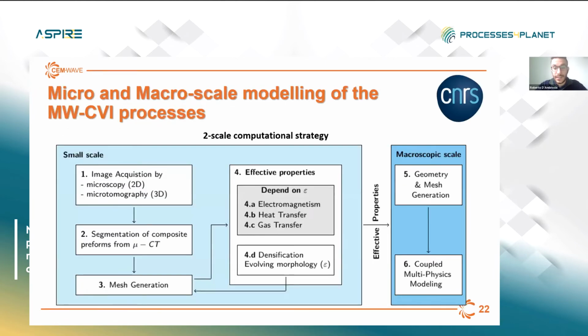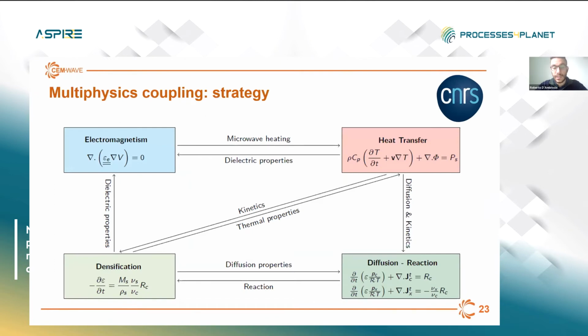Another crucial activity regarded the multi-physics, multi-scale model of the microwave CVI processes, which have been carried out at CNRS in Bordeaux. Here, it is depicted the modeling strategy, which covered 3 different scales, from the intra-fiber bundle scale of tens of micron up to the whole part scale. You can see that in order to model the microwave CVI process, we need to solve the conservation equations for 4 different physical problems. And also, we need to know the laws providing the change of the geometrical and transfer properties during the infiltration process.